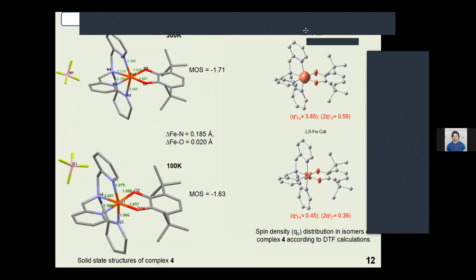X-ray data on complex 4 collected at high temperatures indicate the high spin state of the metal center again. The calculated MOS for complex 4 is minus 1.71. Interestingly, the calculated MOS index in this case is the lowest among the studied compounds. Significant changes again were observed of metal-donor atom bond lengths at low temperature due to high spin to low spin conversion.